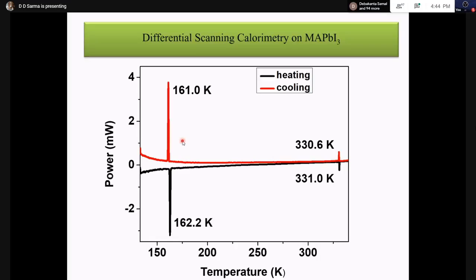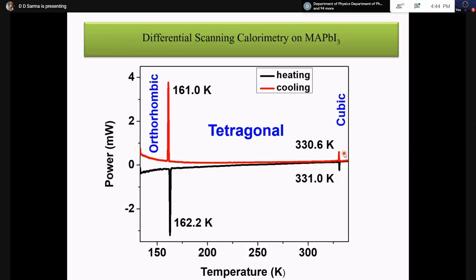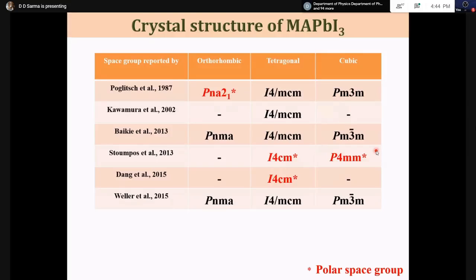In this range, which is the most important one, room temperature and somewhat above, and all the way down to 160 Kelvin, it has another crystal structure, and below that it has another crystal structure. The crystal structures are also very well known, and there's no controversy. This useful crystal structure is tetragonal. The low temperature structure is orthorhombic, and the high temperature structure is cubic. We know that. But all of these can also be polar and non-polar, and this is the information that was available to us when we went into this.